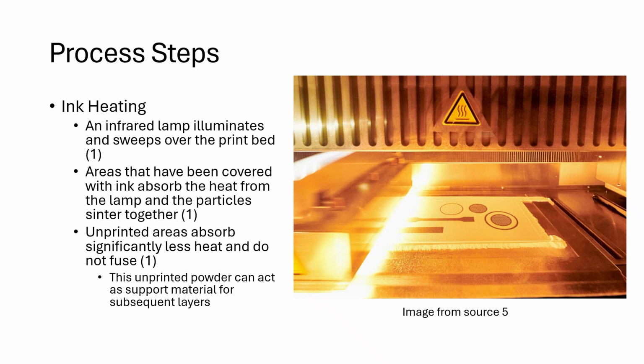Once the ink has been printed onto the top layer of powder, an infrared lamp sweeps across the bed. The printed, darker areas absorb more heat and sinter. The lighter, unprinted, and unsintered powder stays cool and loose. That unsintered powder conveniently supports the next layer, so no extra support structures are needed, like with the fused deposition modeling method.